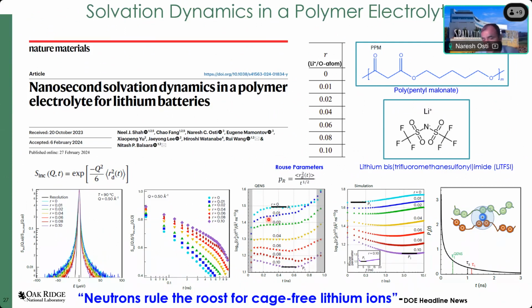But at higher concentration, you can start to see the decrease in the Rouse parameter, and then it starts to form a plateau. That plateau is coming from the formation of the solvation shell between the lithium ion and the oxygen atom of the same monomer of the same polymer, or that of the monomer of a different polymer. And you can see this plateau is there, and after some time the Rouse parameter starts to increase. That means the solvation shell starts to break up.